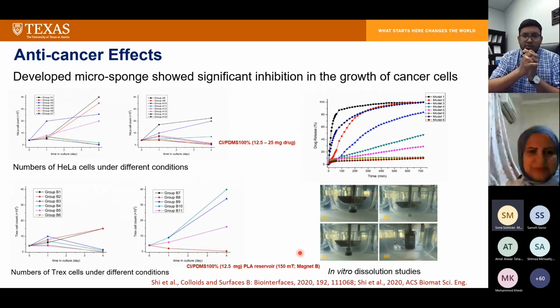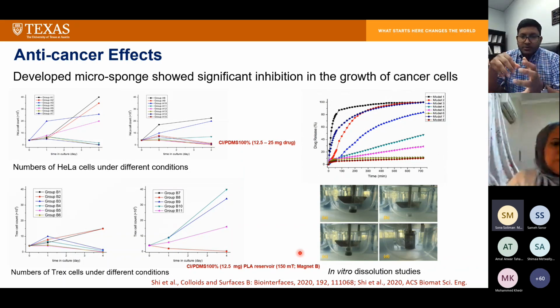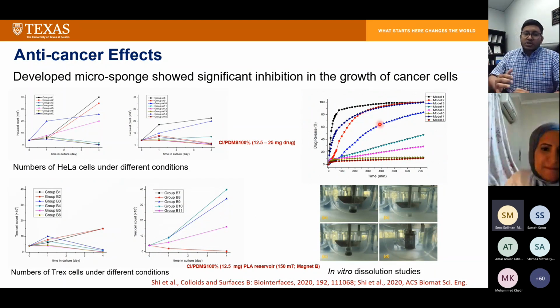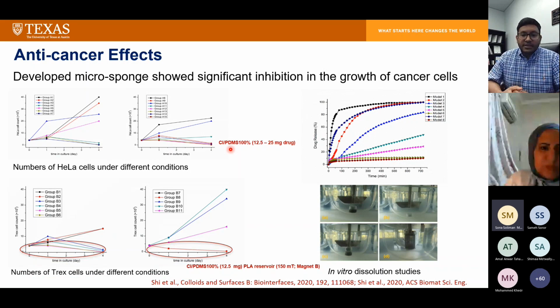So our main focus was to look at how precisely could you control the release from this chamber or from this magnetically triggerable 3D printed drug delivery system, and what can be seen from this drug release study over here. By switching on or off, you could easily modulate or control the release of the drug from the system. When we did the in vitro cell culture study on different cancerous cell lines, what we found that when the formulation was truly optimized, we could actually inhibit the cancerous cell growth significantly. So this was a really good proof of concept study to show that 3D printing can be successfully used for magnetically triggerable drug delivery systems.